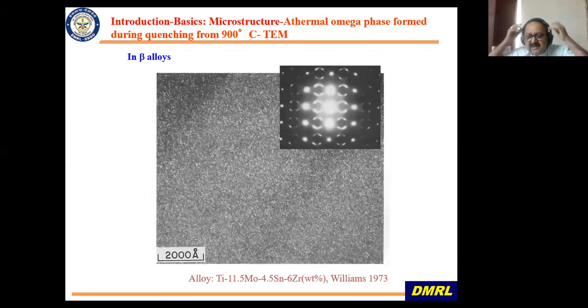Okay. Then the other thing that happens in mostly beta titanium alloys is when you quench them or age at very low temperatures, you get what is known as omega phase, and these are very fine. Normal microstructure, unless you do TEM, you will not be able to see them. But you get very, very fine precipitation of what is known as omega phase. This is a hexagonal phase, and it causes embrittlement. So beta alloys, you should never age at lower temperatures. That is roughly below 450 to 400 degrees centigrade. Again, varies from alloy to alloy.